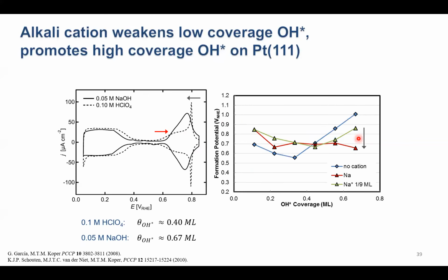Really, the only difference with the flat surface is that now we have to pay very close attention to the coverage of the cation that we're considering. If we really want to approach being quantitative with these methods, we have to consider that different cations can adsorb to different coverages on our platinum-111 surface. And so that coverage not only explains the effect of pH, but also differences between the cations.